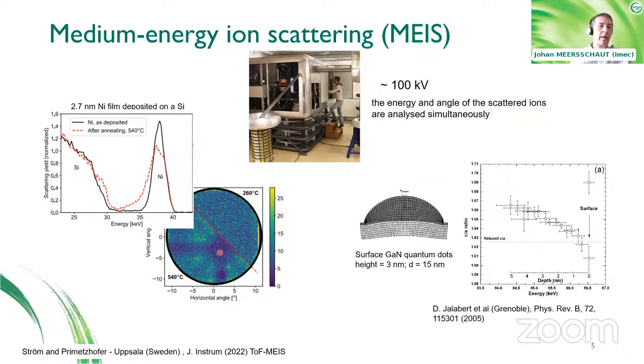And you will see here that after the sample has been heated to 540 degrees Celsius, some dark spots appear. This has to do with the blocking of uppermost atoms, avoiding that the scattered particles end up in the detector. This phenomenon is termed the blocking phenomenon. So this blocking phenomenon can be related to, or is very similar to, the diffraction of X-rays emitting from a sample. So you can understand that the points of blocking in the backscattered spectrum tell you something about the crystallographic orientation in the sample.